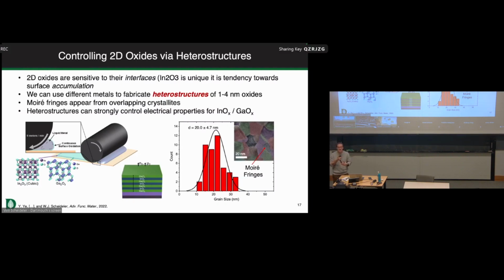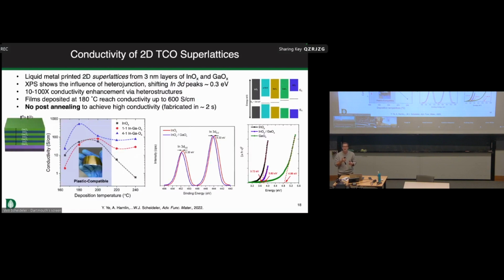As soon as you introduce dopants into a material that are aliovalent, you typically have some scattering mechanisms that it induces. If you do this with a remote doping approach at the interface, instead you've avoided introducing those scattering centers. But just like I showed you earlier, with this roll-based method, we can still make the grains large. We can mitigate any of the grain boundary scattering also at this larger carrier concentration. So it has a lot of the properties we might want in this case if we're trying to make a transparent electrode. So thin film transistors, one application of oxides.